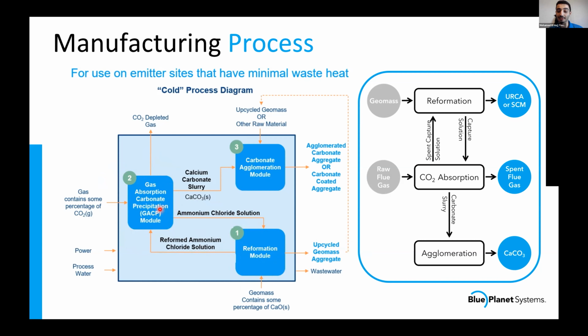What comes out of there is calcium carbonate and a liquid. That liquid, once it's separated, is ammonium chloride, which goes straight back into the reformation module. So we have a circular process there, really minimizing the amount of chemical loss in our process. That slurry is further processed to make the rock that I showed in the slide before. What's nice about our process, I'll get into a little more, is we're taking CO2 directly from flue gas. The material that comes out, this upcycled material, can also be mixed with the calcium carbonate. That's not what I showed in the slide before, but you can marry the two products to spread that CO2 out to a larger amount of products if need be.